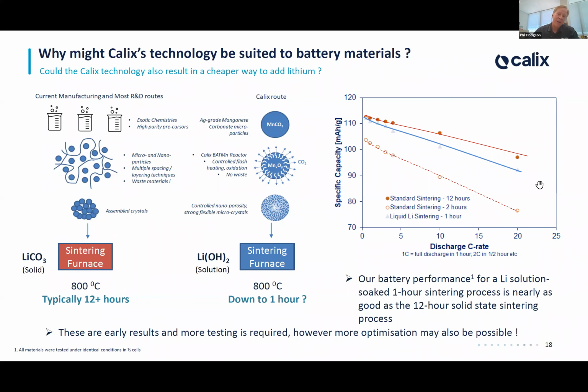Well, here on the right-hand side, we've got an interesting graph that looks at, here's your standard 12-hour sintering, this very top curve here, and here's the performance in terms of, say, specific capacity versus discharge rate, or that power side. And so here's a typical 12-hour sintering route, and here's what happens when you drop that sintering time with this solid methodology. So you drop that sintering time to, say, 2 hours, and you can see the dramatic performance reduction that occurs in the battery. Well, here's where we've used our liquid lithium hydroxide solution doping technique, and only sintered for 1 hour. And you can see here, we're not quite up at the 12 hours yet, but we're getting close.